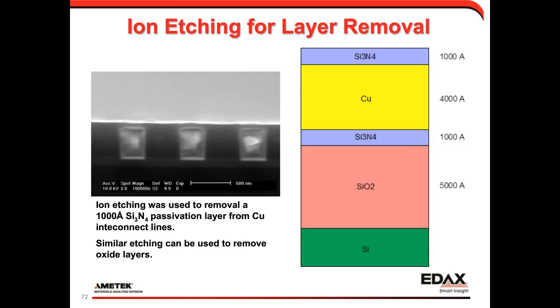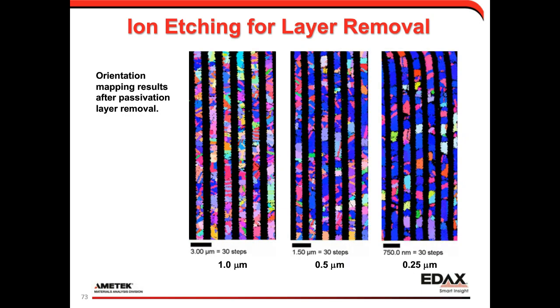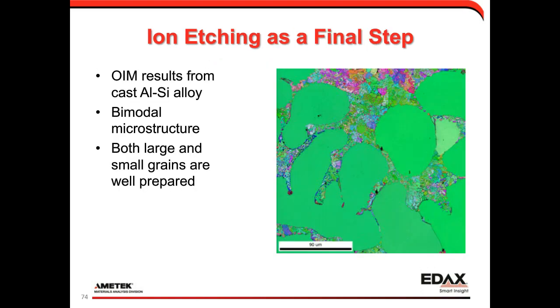And we also use broad beam ion etching to remove passivation layers from copper interconnect lines. So on the left there, you can see the interconnect line with about a 100 nanometer, 1,000 angstrom silicon nitride passivation layer. So again, going in with a glancing angle, remove that passivation layer, and then we can see we get nice orientation maps from the different size lines in the structure. And those are all examples of materials that can be tricky to do conventionally.